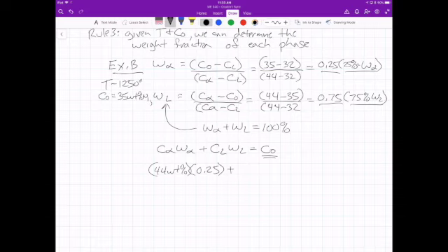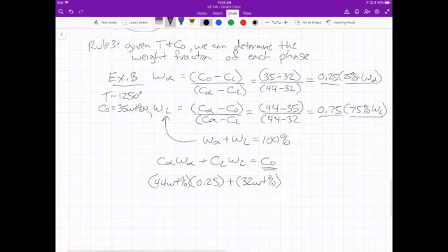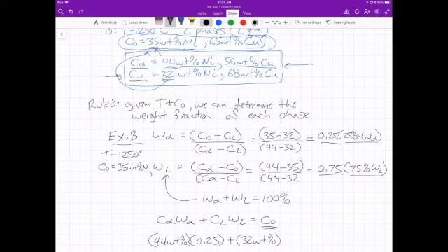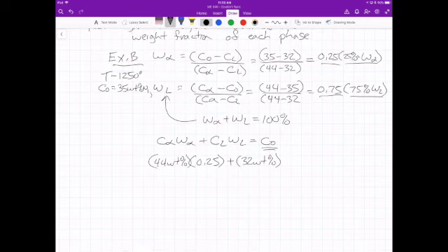Plus my concentration of liquid, which was 32 weight percent. All right, I'm taking those right off of here, 44 and 32. And there's 75% liquid. If I multiply that through, I will get my C naught, which is 35 weight percent. Okay. All right, so let's go on to the next part here.